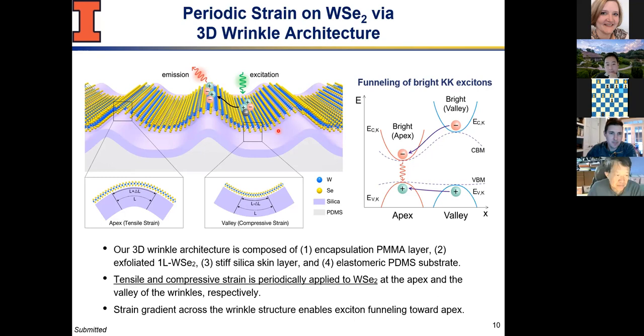And as you can expect from this drawing, if it follows what we expect it to behave, then at the highest portion, since this is a conformal wrinkle, I'm probably expecting some tensile strain on top, if there's not much slippage and things work as we want them to. Or at the bottom, the valley of your wrinkle, we're looking at some compression. And at some point in the middle, there might be no strain. So we have some sort of strain gradient across the real space that we're looking at between apex and valley.